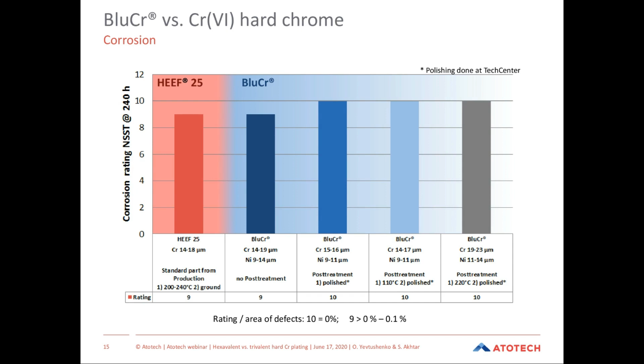And the parts deposited from the HEEF 25 process were taken from production, and they have seen post-finishing like heat treatment, and they were also ground. In the case of parts deposited from blue chromium, we present comparisons of different post-treatment conditions. The first one had no post-treatment, so parts as plated. And for these parts, you can see the same corrosion rating as for parts from the HEEF 25 process.